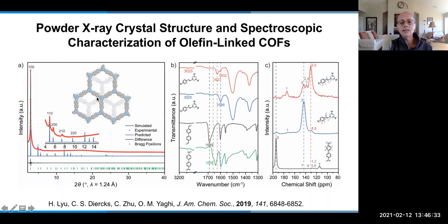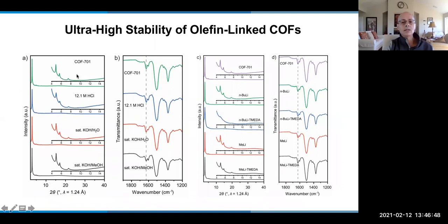It's a slipped graphitic layer. As I said before, we use IR and NMR, carbon-13, nitrogen-15 labeled NMR, to make sure of the completeness of the structure. But you see here the stability. This is the COF, the original COF with olefin. This is the same COF with 12 molar HCl, saturated KOH. This is the IR of those. And even n-butyllithium. So very harsh conditions, and the structure is maintained. The linkages are maintained. This is the sort of stability that we need to be able to use these materials for carbon capture or water harvesting, which I won't discuss too much today.